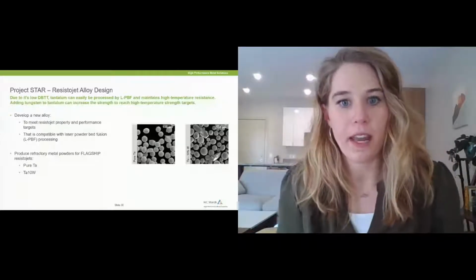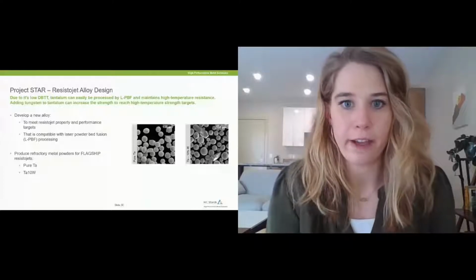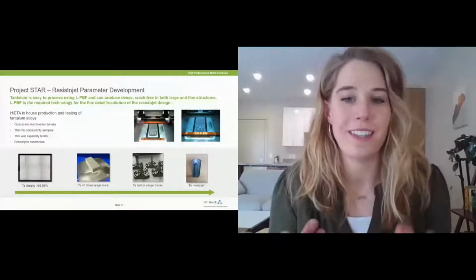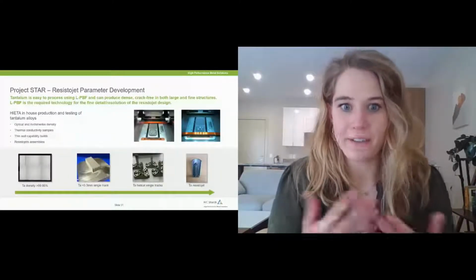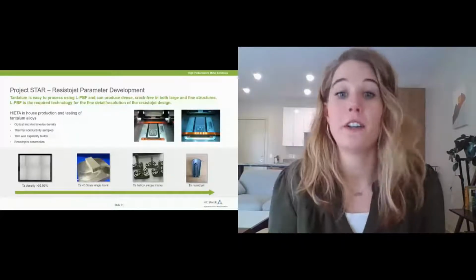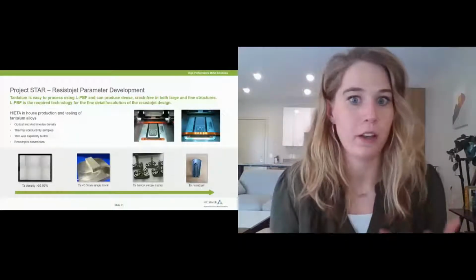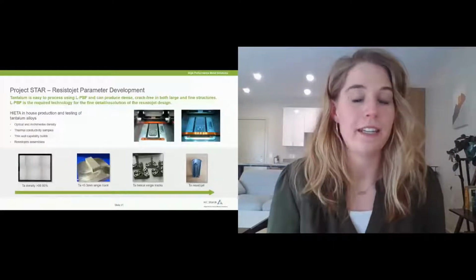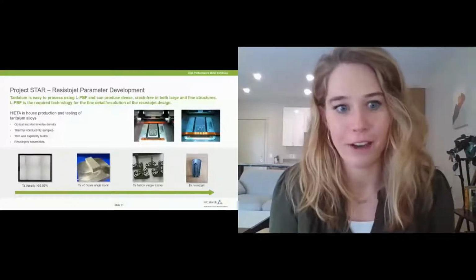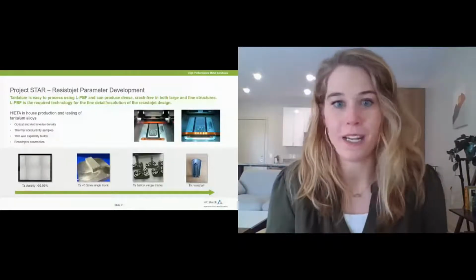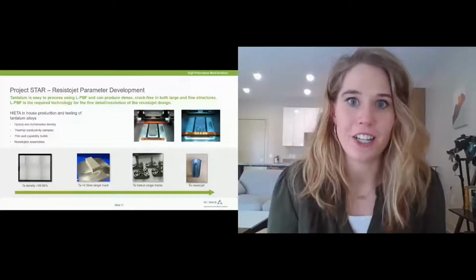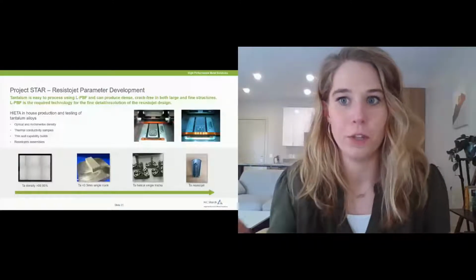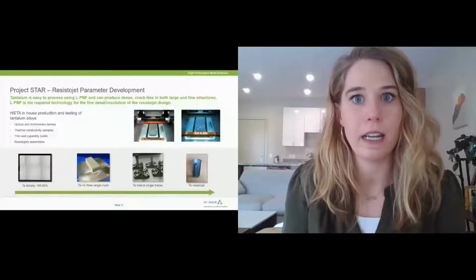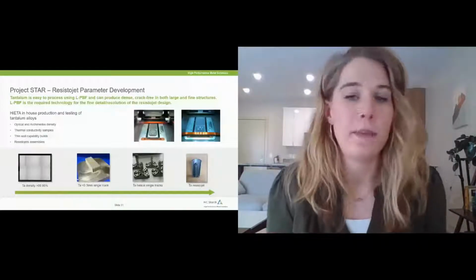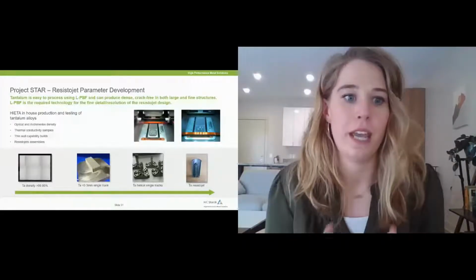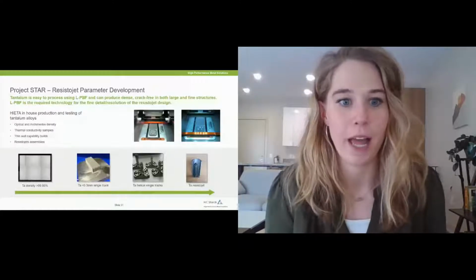This is just some of the work that HIETA did on their Renishaw AM500 machine. Even though these tantalum materials have very high melting points, you can use standard powder bed fusion platforms with the regular 400 watt laser to create densities greater than 99.5%. This is extremely important because being able to print at such high densities really reduces the amount of post-processing work needed for this application. No hipping was needed to get to this density, so very printable as is.